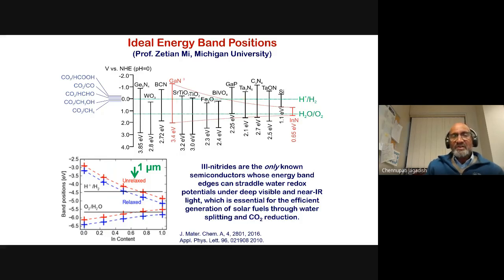You can see that some semiconductors can do that, but the challenge is that gallium nitride is very good, but it doesn't absorb visible light. It only absorbs UV light. Whereas indium nitride only straddles one of these potentials. But if you go for indium gallium nitride, which can have a smaller band gap, which is good for absorbing visible light, and also straddles the redox potentials of water, it can be a very good material from that point of view.